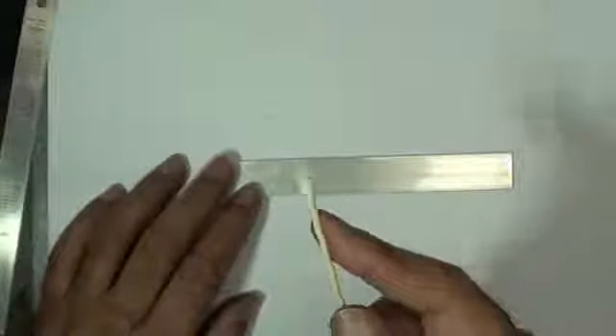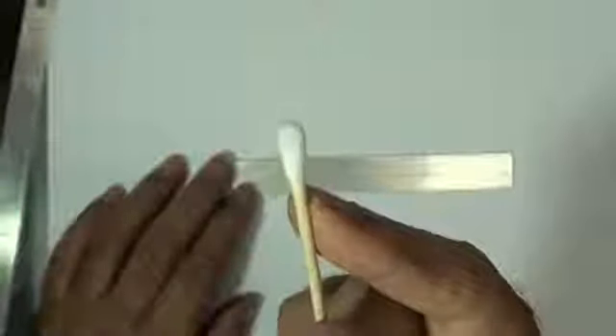This is going to be bonded with an adhesive called M-Bond 200, which is a cyanoacrylate. And those particular adhesives are very sensitive to the acidity of the surface. So to ensure that we cure the adhesive correctly and establish the best possible strain gauge bond, we're going to use the MPrep Neutralizer 5A to bring the surface pH back up to neutral. And VJ's doing this with a scrubbing step in the direction that he sanded. We can see that the surface is now coming out really clean because there's hardly any dirt seen on the cotton tip. Right.